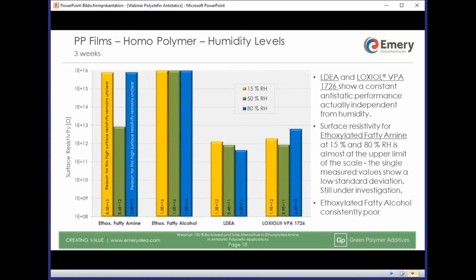Final results slide on PP films, homopolymer, and influence of humidity. And now let's start on the right-hand side. LOXIOL VPA 1726, antistatic performance is good and not depending too much on humidity. LDEA, the same. Ethoxylated fatty alcohol, in line with previous results, no performance. Ethoxylated fatty amine, strange. The result at standard humidity 50% is in line, but at 15 and 80% it is at the upper end of the measuring range. Standard deviation this time is okay.